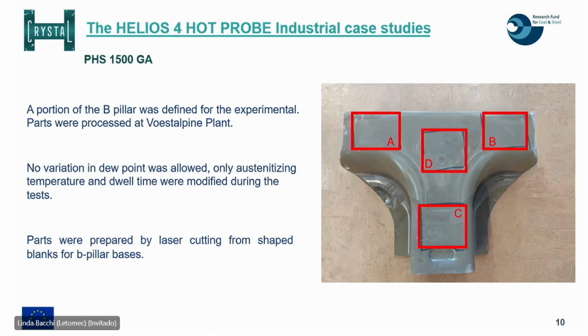The second case study was realized on the PHS 1500. In this case, the material was galvanized, and we defined a different component, which was the B-pillar. Here a part of the B-pillar is represented, because we needed to ship these parts from the Voestalpine plant to our lab, since due to the COVID situation there was no way to reach the plant. So we received the component very fast, and we performed the measurement of diffusible hydrogen in the 4 areas highlighted here in red squares.